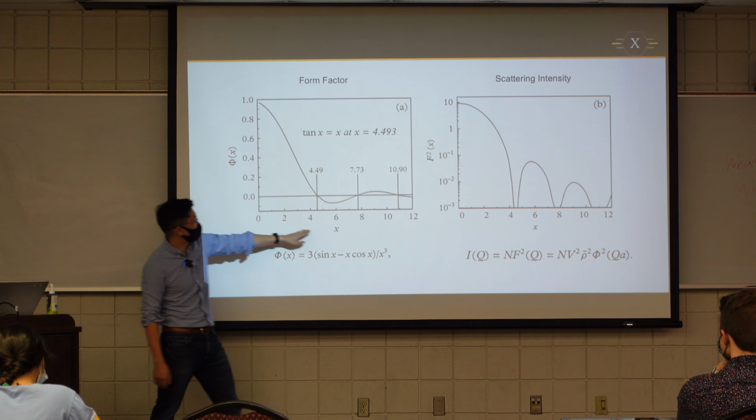So what we're plotting is log intensity versus the Q scattering vector. And you will see almost the same shape, but it slightly has a different decay value. We're going to talk about why there's a decay in high Q in just a second. But you can observe this local minima and mark where the Q value is and use very simple equations to calculate the radius of your particle, okay? That you can do.